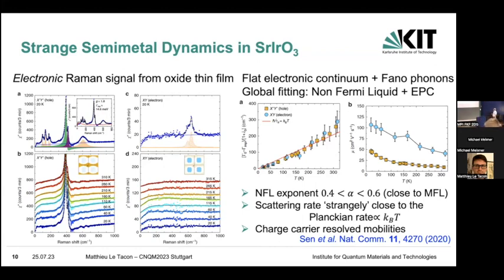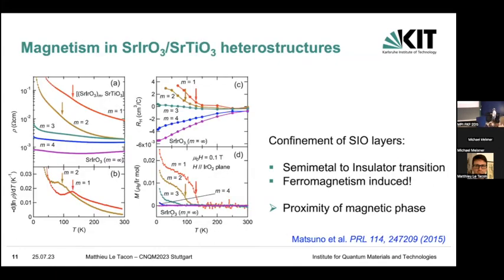Okay, so that's an interesting system, but what made it even more interesting is this work from the group of Hide Takagi a few years back. If you now confine this strontium iridate, so you go from a semi-metal, you grow a superlattice with strontium iridate and strontium titanate. When you reduce the dimensionality, making very thin layers of strontium iridate sandwiched between strontium titanate, you see that you go from a semi-metal to an insulator, and that insulator happened to be ferromagnetic as well.